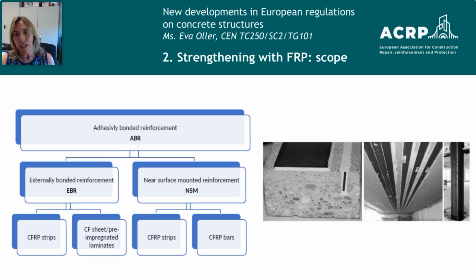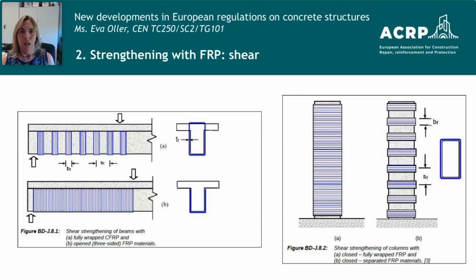The other technique is near surface mounted reinforcement, which consists of performing a slot cut in the concrete cover and then embedding a CFRP strip or a CFRP bar. So shear strengthening is required if the average shear stress is larger than the shear strength of the original reinforced concrete element. Then there are different configurations that are considered in the Eurocode.